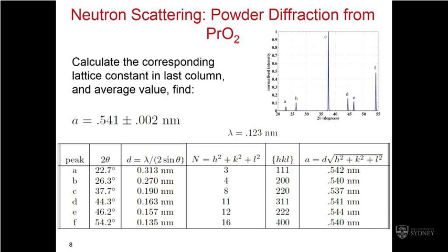And so you get an estimate of the lattice constant from all of those intensities, and they're all pretty close together. And the deviation, as I said, gives you an estimate of the experimental error. Okay, so that's fine. We've been able to find the lattice constant.